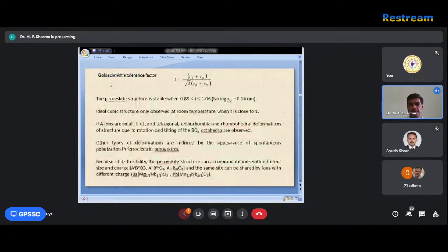Now next, we classify our perovskite structure using the tolerance factor, which is given by (Ra + Ro) divided by root 2 times (Rb + Ro). It is for a cubic structure. When a structure is stable, it is 0.89 to 1.06. Generally, when it is close to 1, it is perfectly cubic. If A is a small ion, then the tolerance factor is less than 1, and a tetragonal or other structure may form due to this.